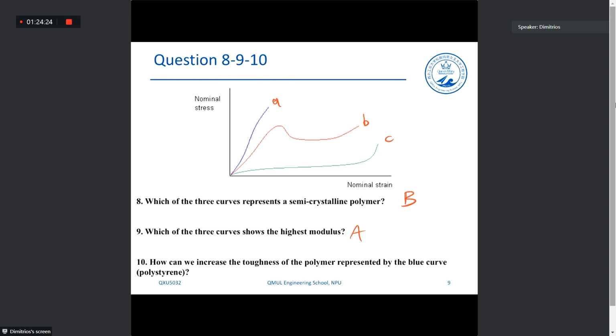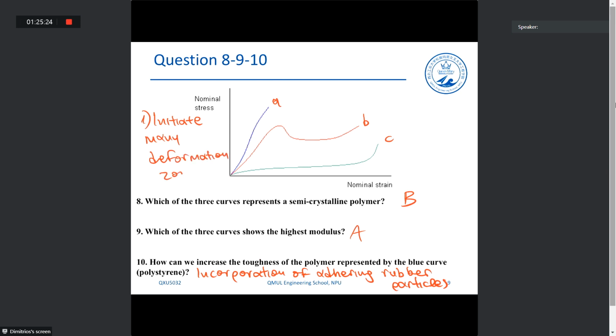Indeed, rubber particles or plasticizers, or in general, blending with softer polymers is a very efficient strategy, essentially. So an answer can be incorporation of adhering rubber particles. And what do those rubber particles do? Essentially, they initiate many deformation zones. And secondly, they stabilize cracks or dissipate crack growth.